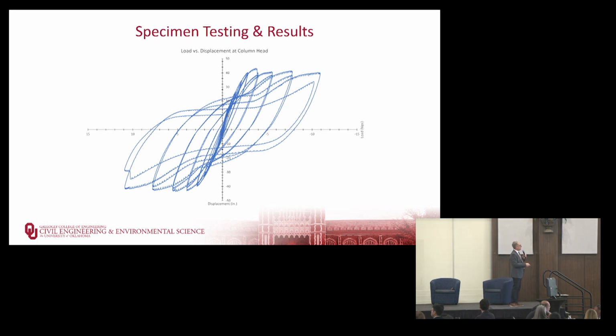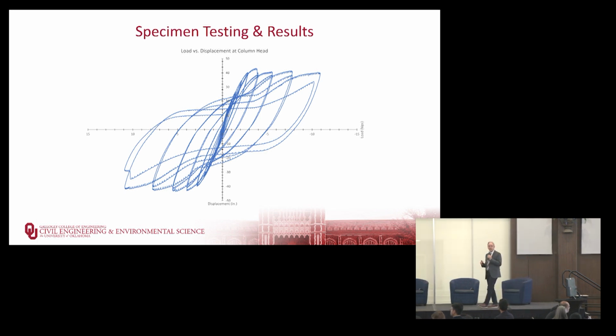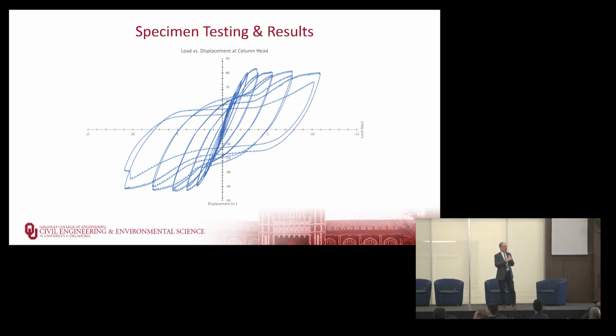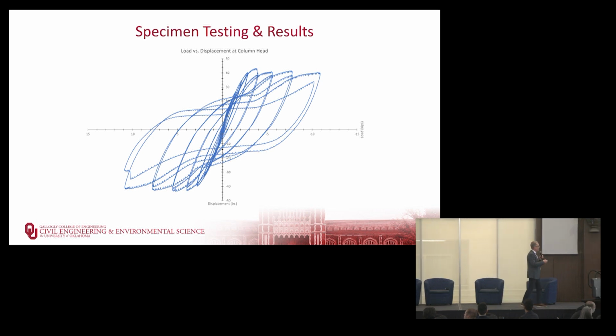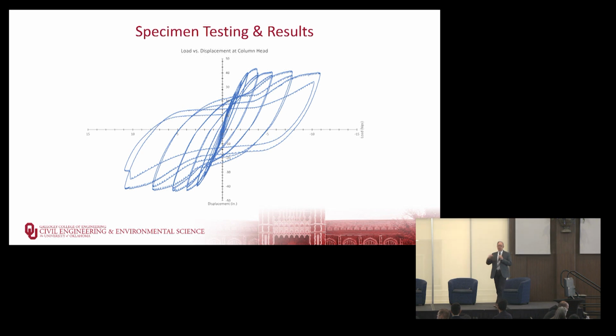And you can see there's some drop off in capacity. We had a peak here at about 3.5, 4 inches of 42, 43 kips. We're losing a little bit, but we get pretty close. So it stays fairly consistent. It has a lot of ductility and a lot of resilience, right? We're talking about pushing this 8-foot tall column 2 feet, from 1 foot in one direction to 1 foot in the other direction. And then we stopped at close to 12 inches because our actuator didn't have any more stroke. And that was the end of the test.